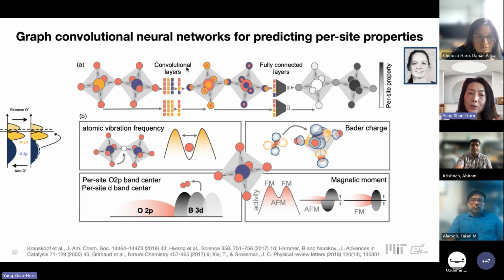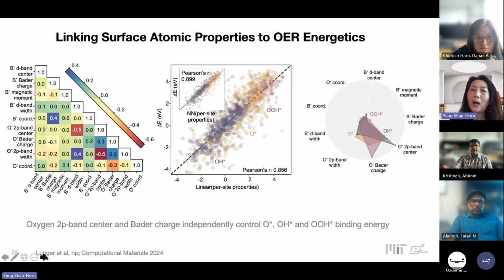And now we are looking at, if we have a different structure, or if we look at substituted compounds, there will be many, many different oxygen environments. It depends on what metal neighbors they may have. Utilizing this method, we can go beyond just electronic structure. We can look at per-site atomic vibrational frequency, per-site oxygen p-band center, Bader charge, as well as magnetic properties.